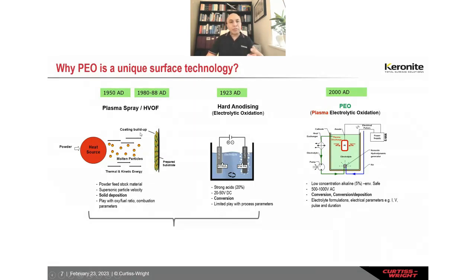The challenge with thermal spray, despite its high attractiveness and versatility, is that sometimes it becomes very awkward on light metals, primarily because of the CTE mismatch, the variation of the expansion coefficient between, let's say, aluminium and the incoming very hot particles, that leads to poor coating adhesion and flaking, etc.